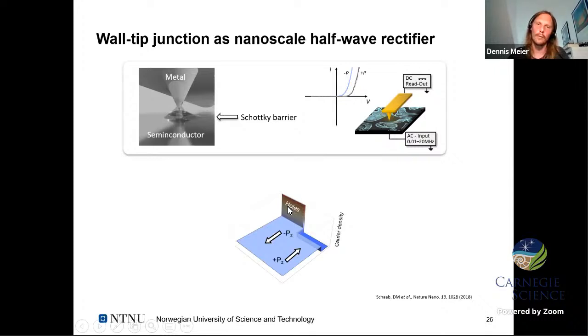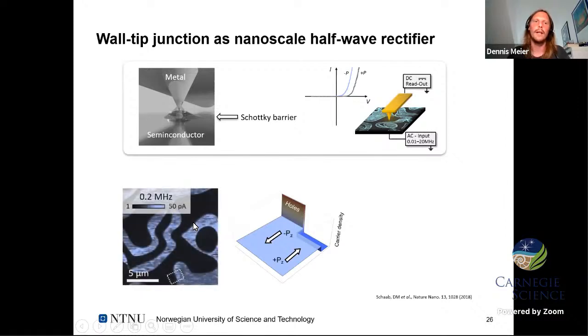In one case, you accumulate holes at the surface, so you have more mobile carriers. In the other case, you deplete holes at the surface, so you have fewer carriers. That affects the Schottky barrier, and therefore gives you different conductance at the two domains when I measure it locally. You can also see that when I now apply an AC voltage. So I go plus and minus with the applied voltage and measure the integrated current. You see, one domain is bright, the other is dark, so one is conducting more than the other.